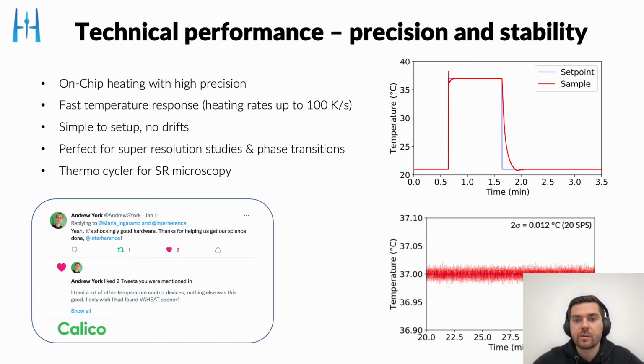The fast thermal response is shown here. The blue is the set point and the red curve is the actual sample temperature. You can then program arbitrary temperature profiles, and the sample temperature follows accordingly. With that, you can achieve temperature changes of up to 100 Kelvin per second. And the precision and the simple ease of use is actually what people appreciate about the system.